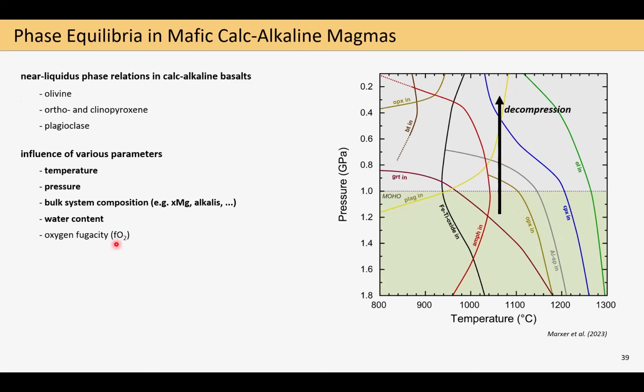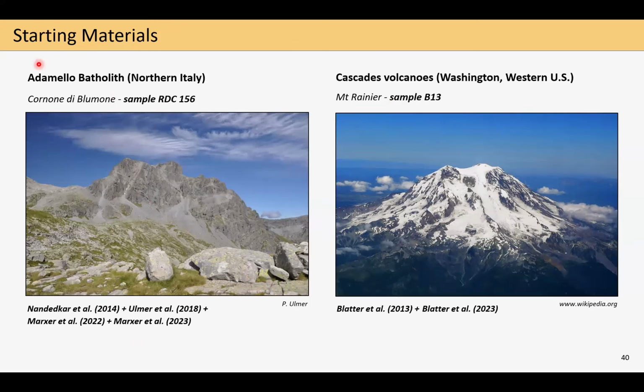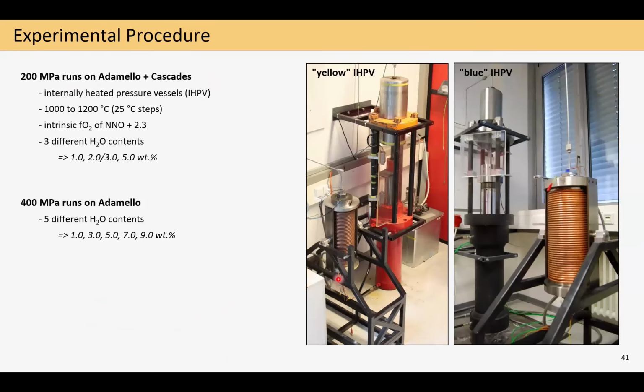And for this project now, to keep the amount of experimental work at a doable level, we decided to use systems which have already been investigated experimentally to some extent in the past, so we can just extend these data sets to upper mid-crustal conditions. And this resulted in the selection of two relatively famous, I would call them, starting materials. One, a basalt from the Adamello, from northern Italy, where I myself and other people from ETH already worked quite a lot. And the second composition is a basalt from Mount Rainier in the Cascades, where Danica Blatter and Tom Sisson already spent quite some time. And what is now less surprising, of course, in the frame of this talk, is that I then did some experiments for this project in our IHPVs.